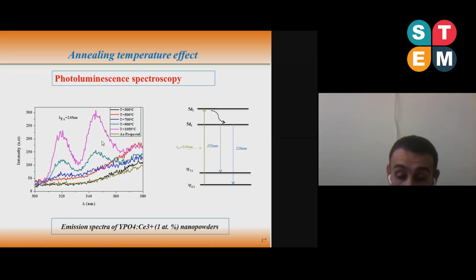The absence of photoluminescence emission in the other powders means that there is no substitution of cerium 3+ in the yttrium 3+ site. It could be explained by segregation of the doping ion in the obtained phase and oxidation of trivalent cerium to the tetravalent state under lower annealing temperature. In addition, at lower annealing temperature, smaller particles are obtained. Hence, the reduction of particle size obviously affected the local environment of cerium 3+ in the yttrium host, probably due to the change in the large surface to volume ratio and the amount of defects on the particle surface.